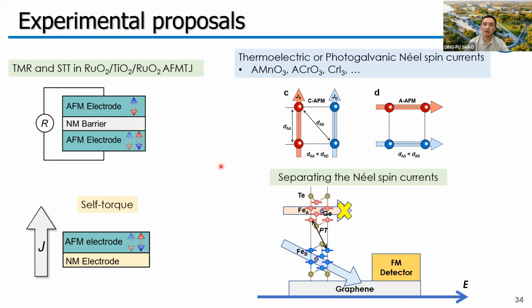Finally, the Néel spin currents may bring new opportunities to these two-dimensional antiferromagnets. For example, we can put A-type two-dimensional antiferromagnets on top of a non-magnetic material, such as graphene. Then, if we apply an in-plane electric field, the Néel spin currents in the bottom layer of the A-type antiferromagnet can be injected into graphene and then detected by a ferromagnetic detector. This separating of the Néel spin currents may generate new opportunities for 2D spintronics using antiferromagnetic materials.